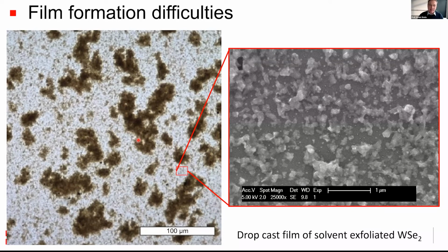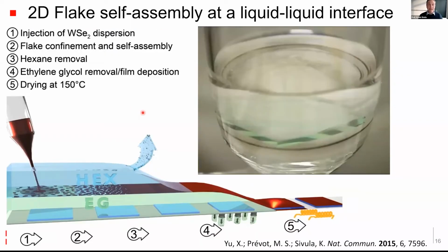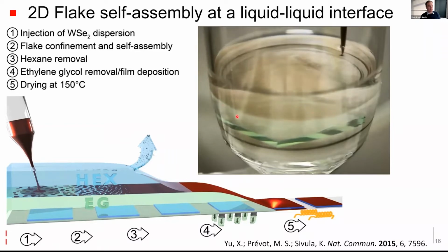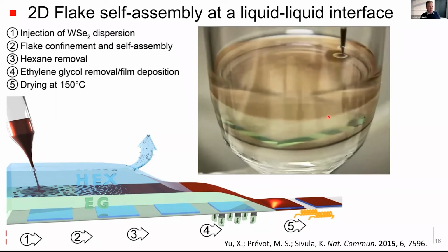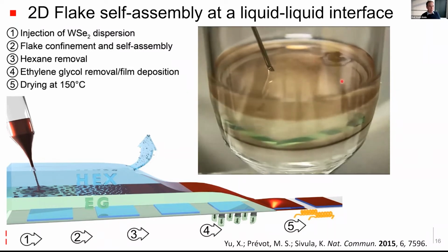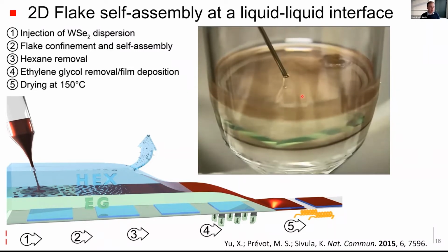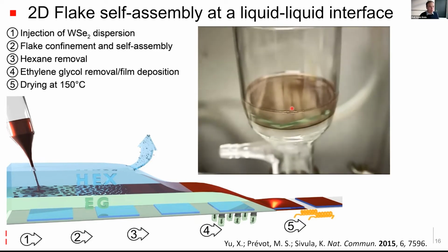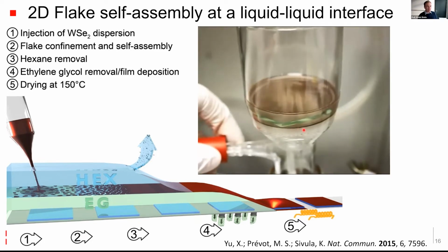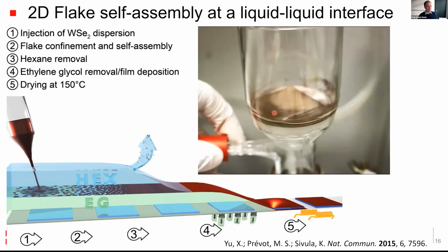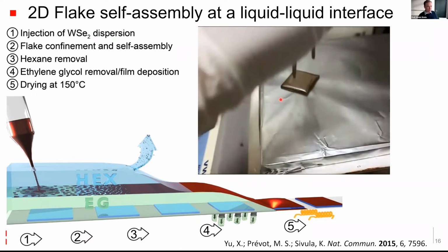So to overcome that, we had to develop a liquid-liquid based self-assembly method. And I'll show you a video of how this works. We can inject these flake dispersions at the interface between two non-solvents, and that confines the flakes at this interface where they reduce their energy. And we can load enough flakes here to fully make a film. And then we can simply remove the top solvent and then remove the bottom solvent through this vacuum filtration, depositing this self-assembled film onto the awaiting substrate below.